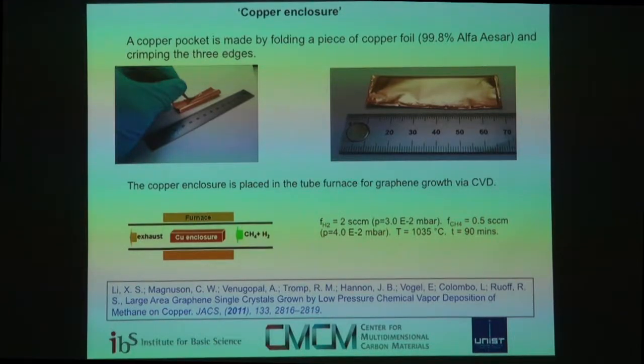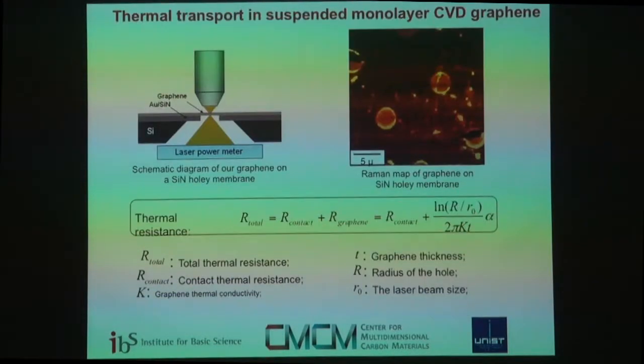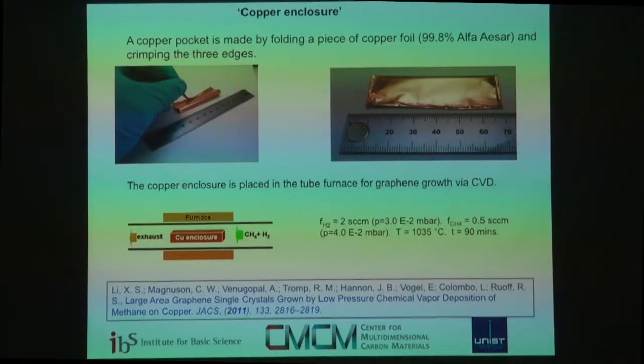So this was a big breakthrough for us because we went from micron islands that merged, or coalesced, or stitched together to hundreds of microns, and then eventually to millimeters, and finally, as I told you recently, to centimeters. So that allows a host of new experiments to be done on large area single crystals.